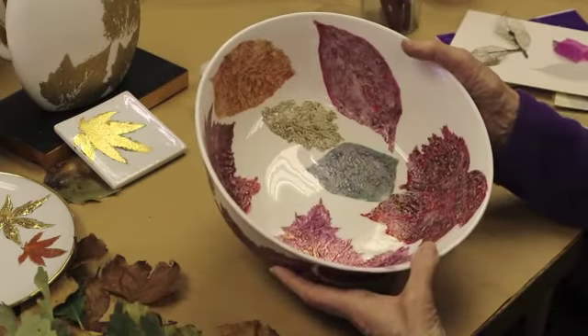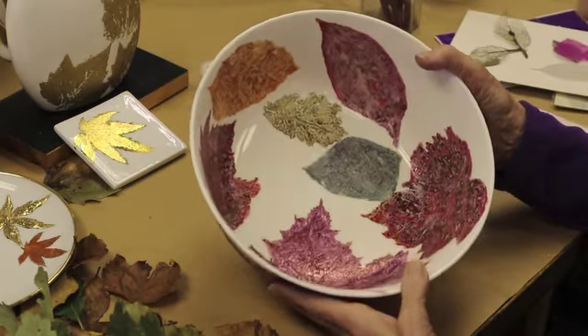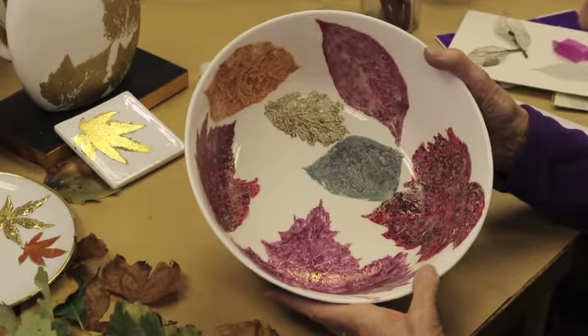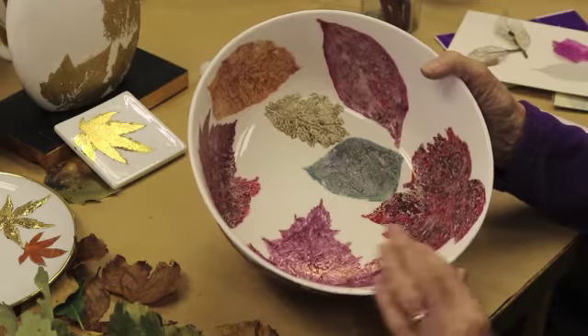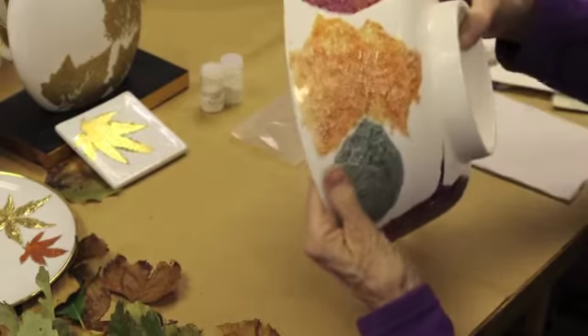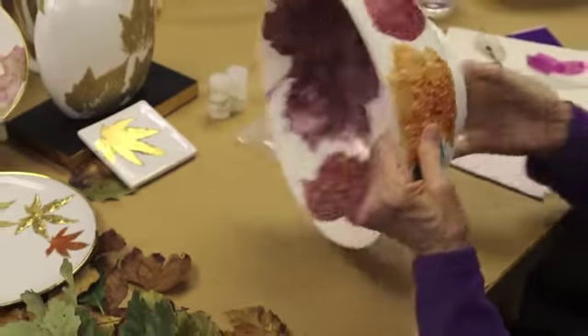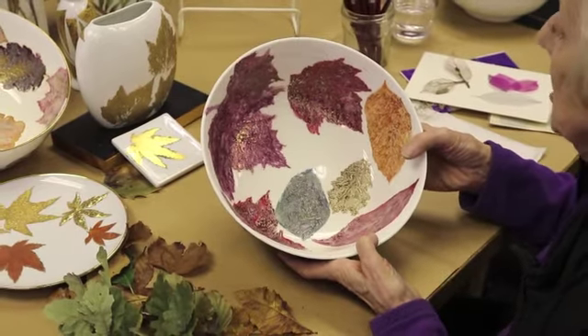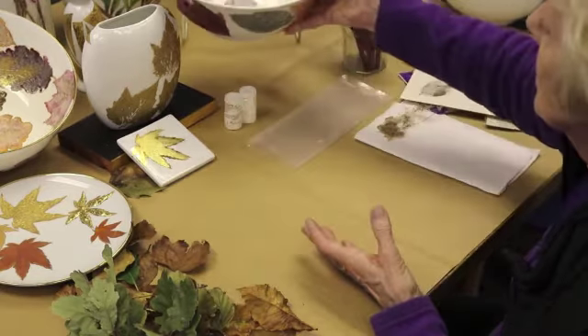This bowl has had its first firing with the glaze, and then when it was fired, I outlined the leaf shapes with different coloured lusters, and then it was fired again. The inside and the outside have all these different leaf shapes on. And when you're firing luster, you fire the luster to 760 to 800 degrees centigrade again. And then after that,